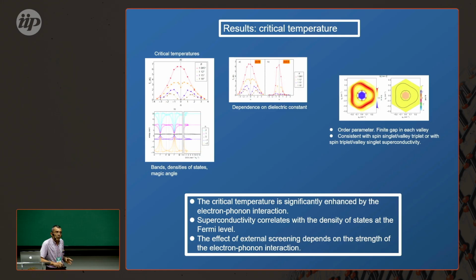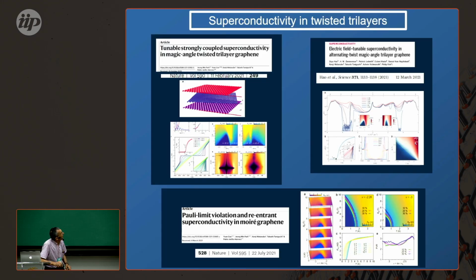So electrons couple not only to the first shell of phonons—the phonons which take you from one point in the Fermi surface to another—you can increase the momentum of the phonon by a reciprocal lattice vector, and it will still be coupled to the electrons in the flat bands, and that way many phonons participate in the mechanism.